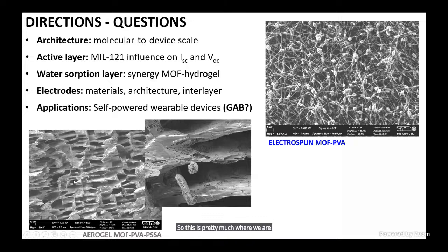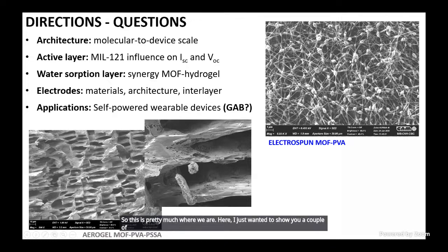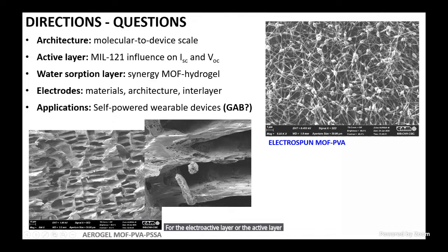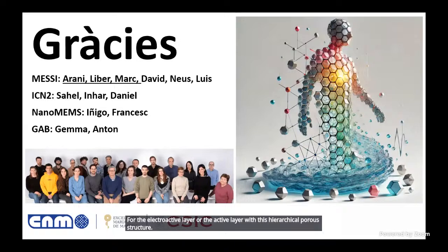Here I just wanted to show you a couple of SEM pictures of different architectures of electrospun MOF PVA for water harvesting, with a lot of surface and the MOF inside the PVA fibers. And this is an aerogel of the MOF PVA PSSA for the electroactive layer, or the active layer, with this hierarchical porous structure. And well, with this, that is pretty much it.